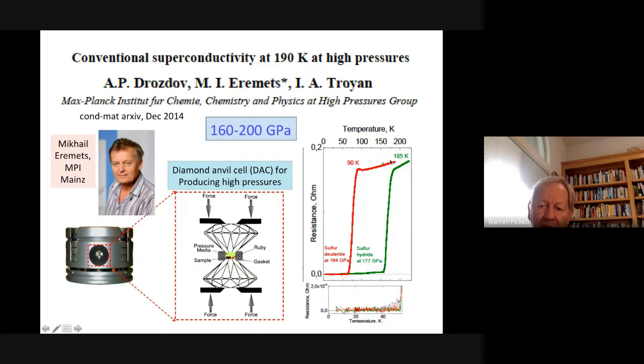So BCS theory predicts that the TC should go down. It's called the isotope effect. And it goes down a lot in hydrogen sulfide, shown right here. But according to the theory, it works well. So that's one demonstration that it is the hydrogen material that is doing this superconducting.